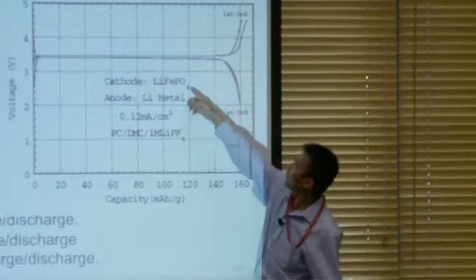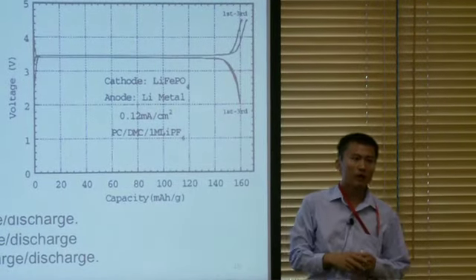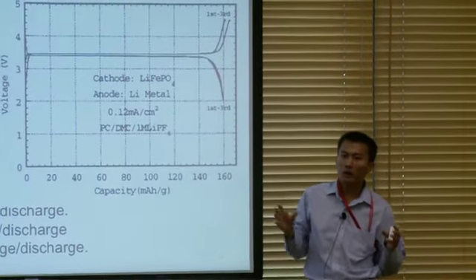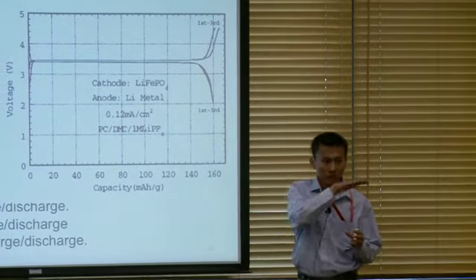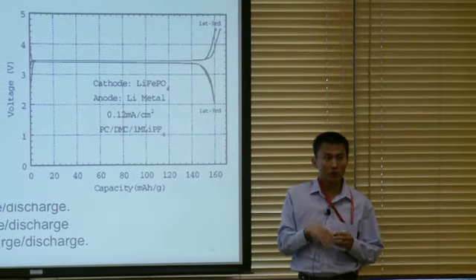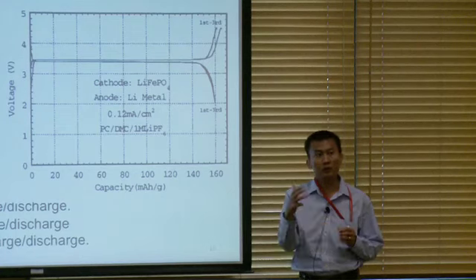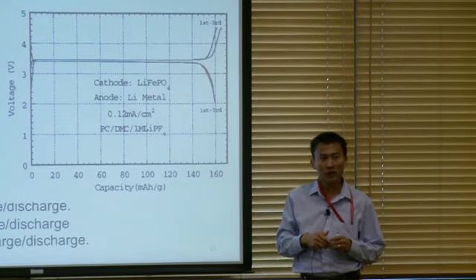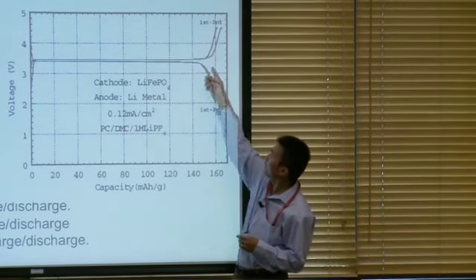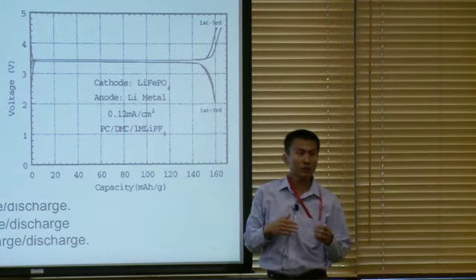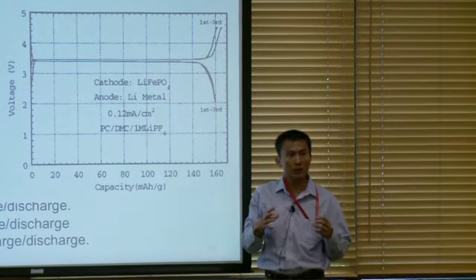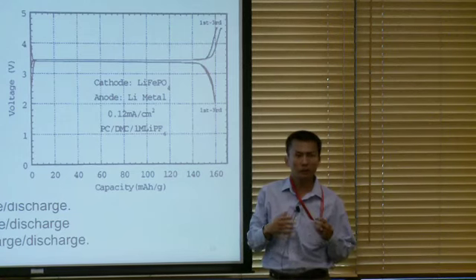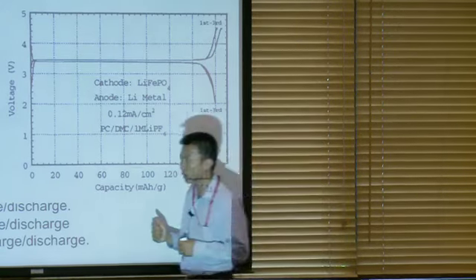this battery, lithium iron phosphate, measured with lithium. The free energy is a constant during the charge and discharge. That gives you the voltage, that's also a constant. And the fact this voltage is very flat tells you it's actually lithium going in, speed is very fast. That doesn't present any kinetic barrier right there. It's a very flat voltage.